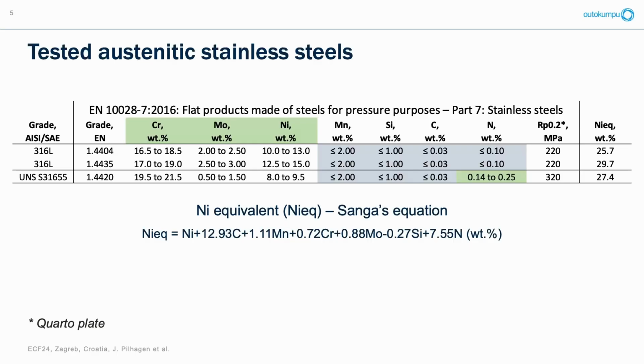2 of them are this 316L in American grade specification. In the European grade, it's actually 2 different grades, 1.4404 and 1.4435. The main difference here is slightly different content of chromium, molybdenum, and nickel. And in this project, we were interested in the nickel content. So in principle, we have one 316L with low nickel content and one 316L with high nickel content.